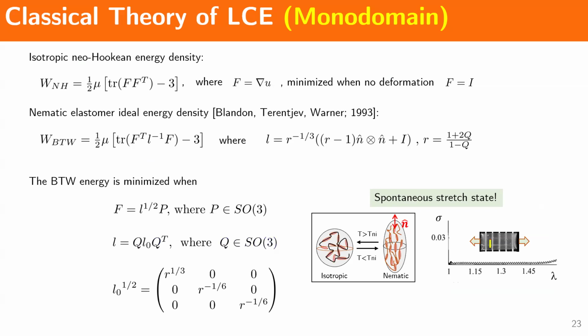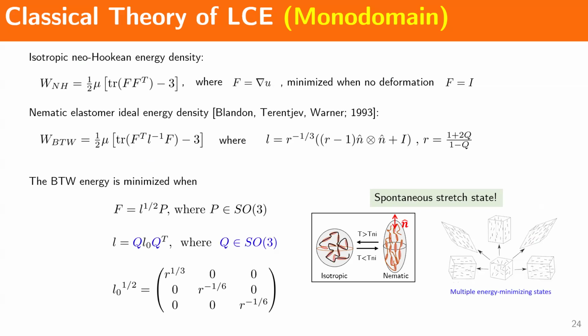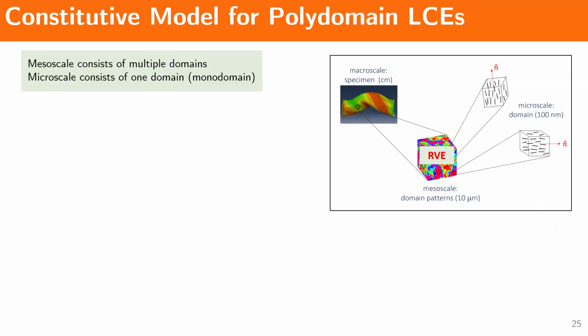Now, we remember that this particular direction can be influenced by external factors, right? In particular, it is unique up to some rotation, okay? So basically what that means is that now you have a degeneracy of energy minimizing states. You have multiple energy minimizing states because the material can rotate and reorient towards any particular external loading direction that you're subjecting it to. So now we no longer have just one energy minimizing state, we have a multitude of these energy minimizing states, right? And so this is captured with this L tensor here. So again, we have a degeneracy of the energy minimizing state. Okay, so that's the classical theory.